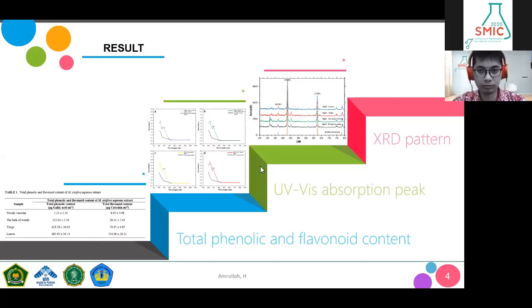In the right figure, we see the X-ray diffraction pattern of magnesium oxide nanoparticles produced from all moringa aqueous extracts. The samples of magnesium oxide nanoparticles show two peaks with highest intensity at 2 theta, 42 and 62, and then three small peaks. The results obtained were verified using the JCPDS XRD standard data number 78-0430, and in this result, no significant characteristic peaks appear from magnesium or other impurities detected on the diffractogram, indicating the high purity of the synthesized magnesium oxide nanoparticles.